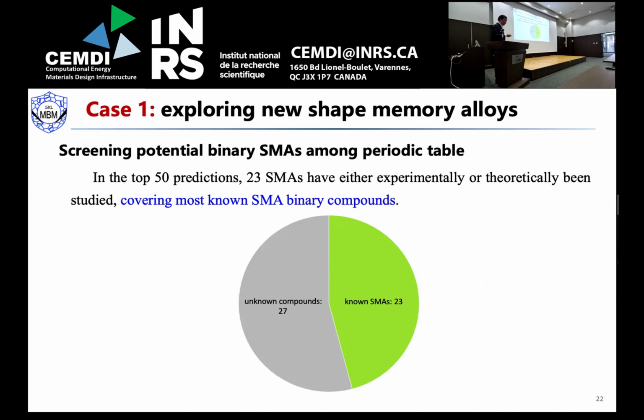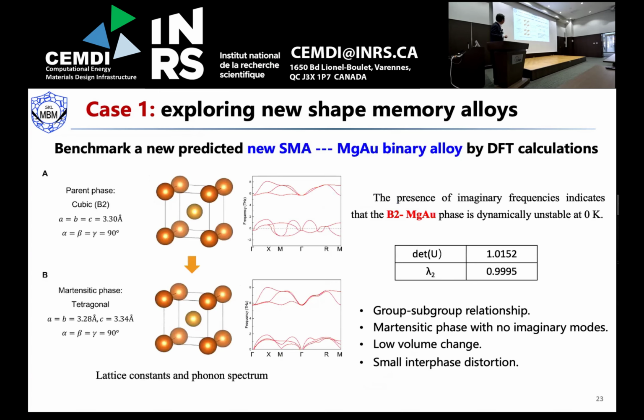So that is just data-driven and combined with the crystal information, so you can predict some new materials without any DFT calculation. Okay, so among the 27 alloys, we just do DFT calculation for one alloy, and this we call magnesium gold alloy. For this alloy we calculate the lattice parameter and crystal structures, and even the phonon dispersion spectrum.